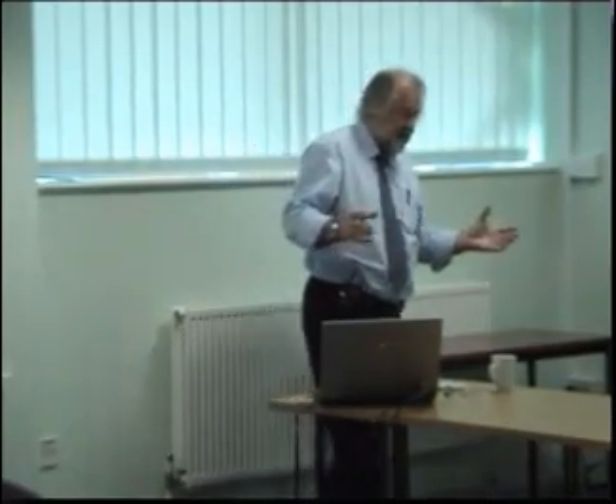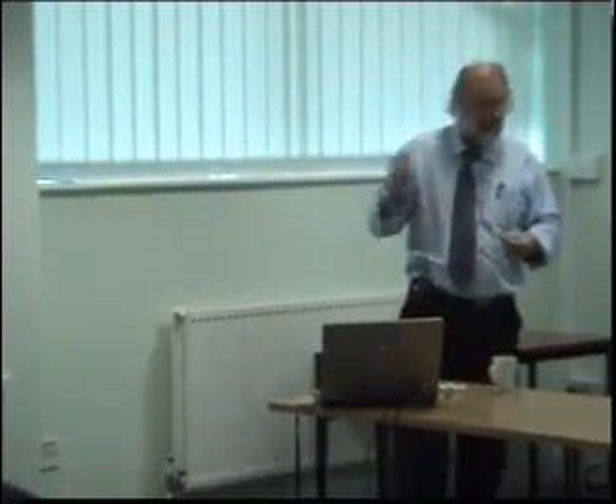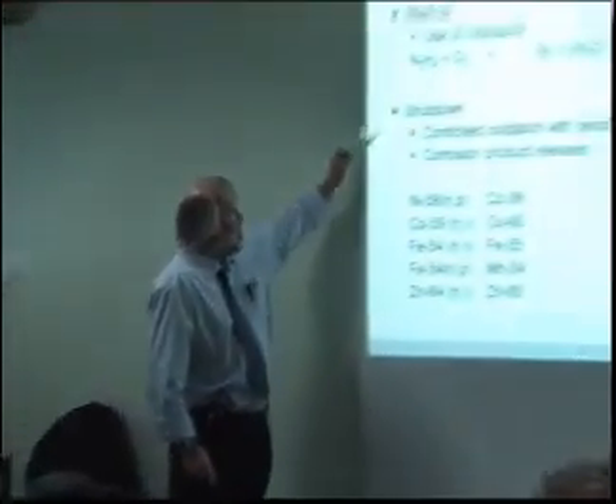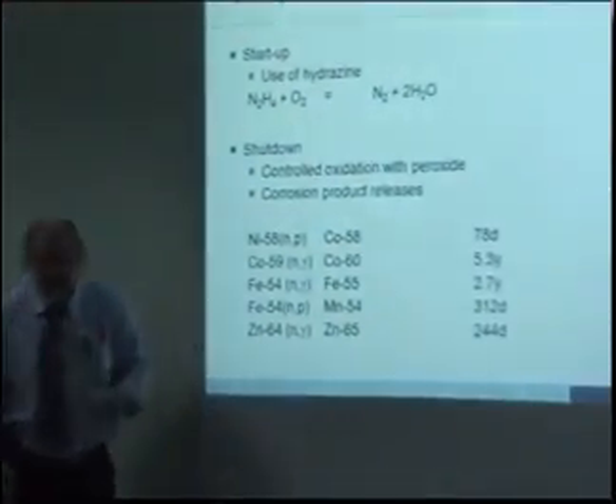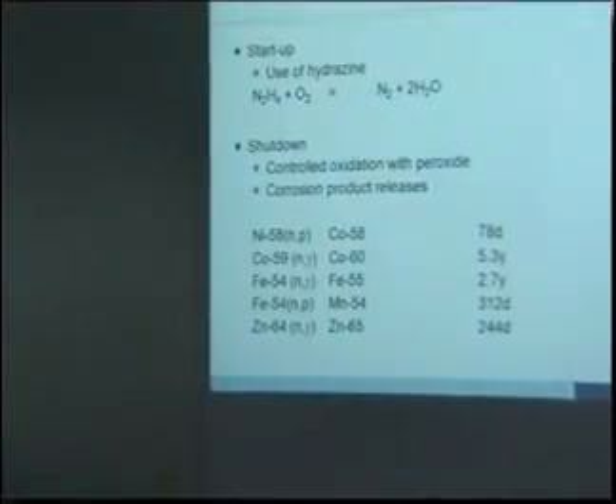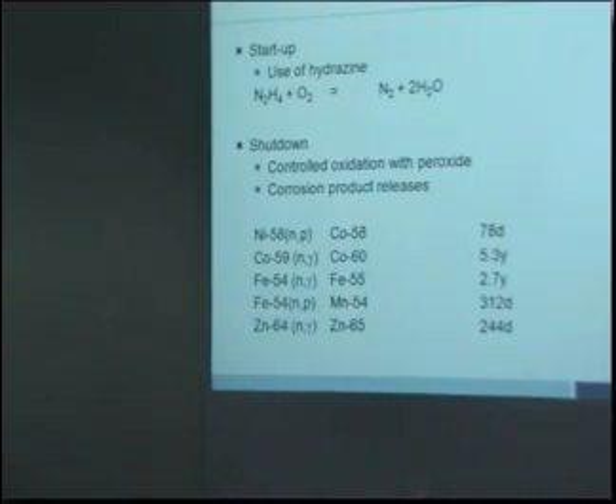At shutdown, you're wanting to take a reactor which is under hot reducing conditions down to cold oxidizing conditions, ultimately you're going to expose the whole thing to air to get the fuel out for refueling. You can do it with air, but it's expedient to do it with hydrogen peroxide. It's a controlled oxidation process. It's rapid. It saves time.